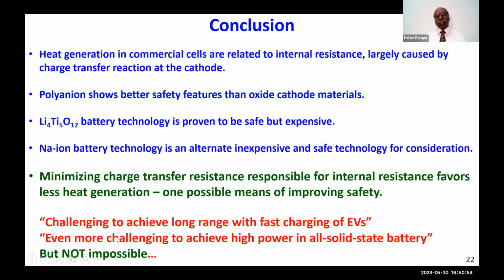Having said that, the take-home message here is it is extremely challenging to achieve long range and fast charging. If you want long range, you need to use graphite. If you are interested in fast charging, you need to use some other technology. But even more challenging is to achieve high power, particularly in all solid-state batteries. If you have closely followed my talk, the charge transfer reaction, the interface between the cathode and the electrolyte, is extremely important. This is the major challenge in all solid-state batteries, but problems can be solved.